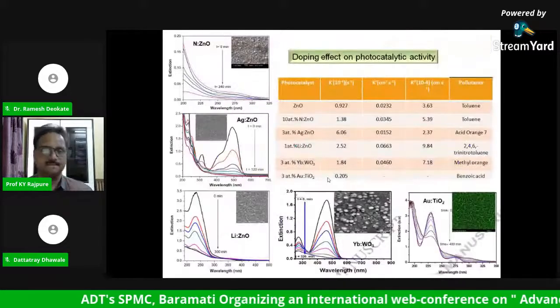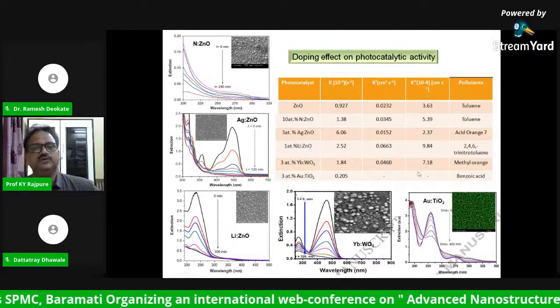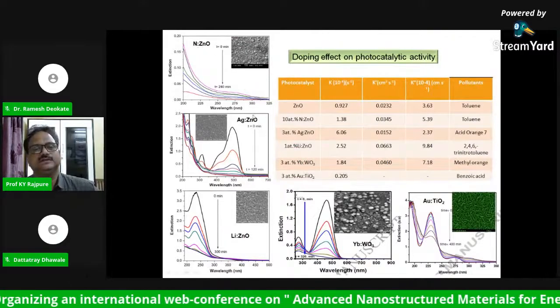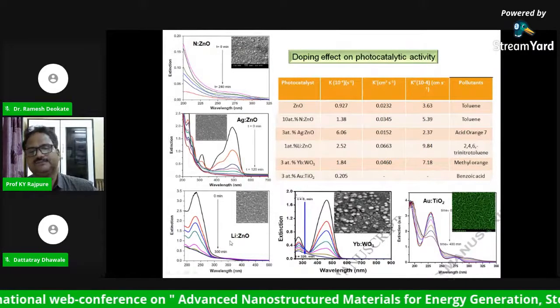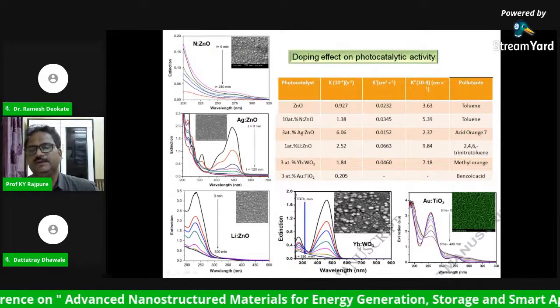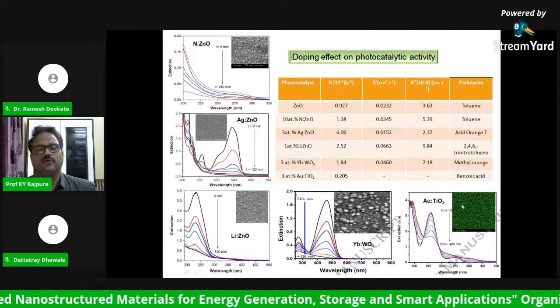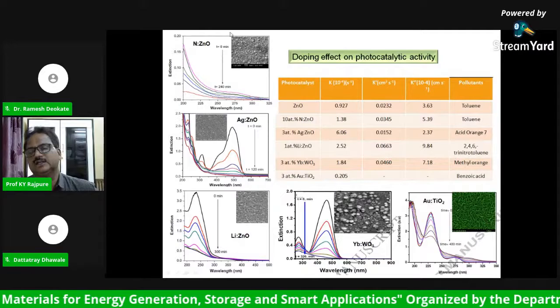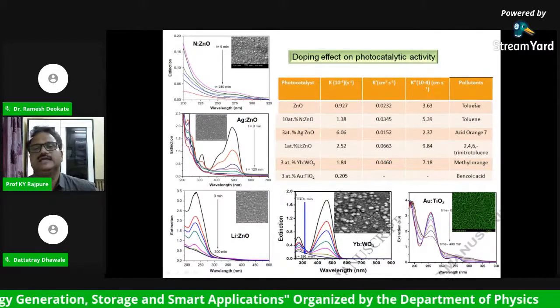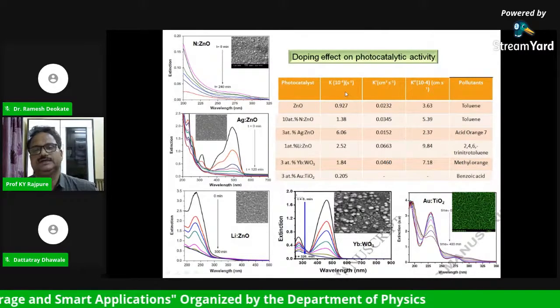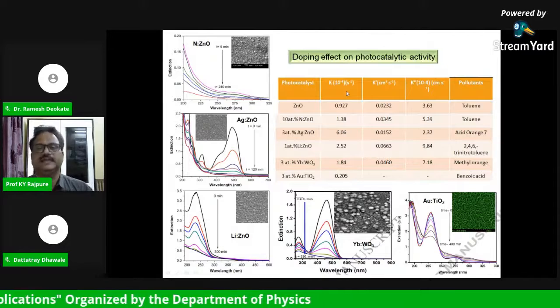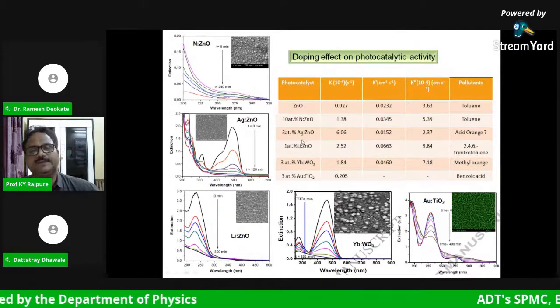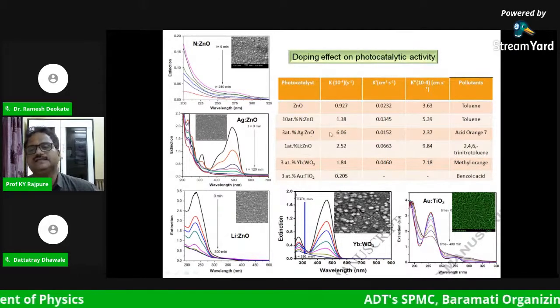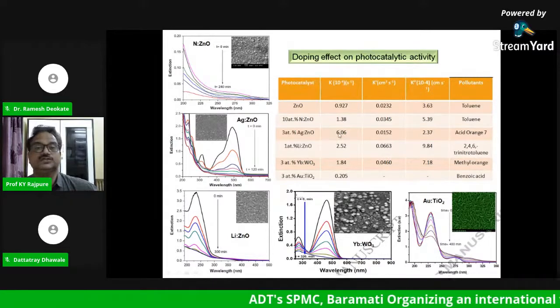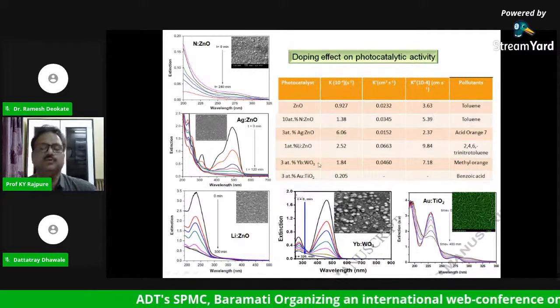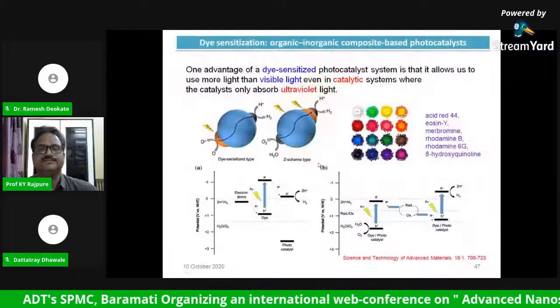So it is possible to tailor the band positions and to harness more visible light by making the material more efficient. As I told, we have used nitrogen, Ag, lithium, Au for doping in zinc oxide, tungsten trioxide, and TiO2. And you can see the rate constant. If the rate constant is high, the photocatalytic efficiency is more. So in the case of Ag doped zinc oxide, we achieved the highest rate constant. And it is possible to improve the photocatalytic efficiency.